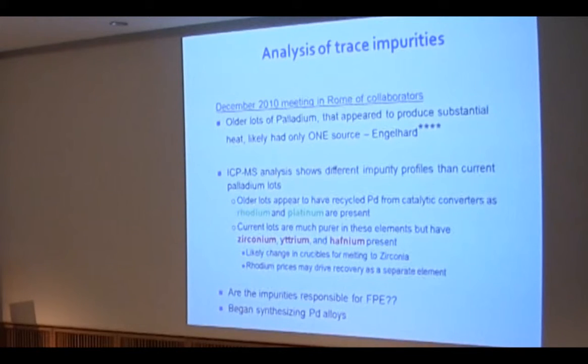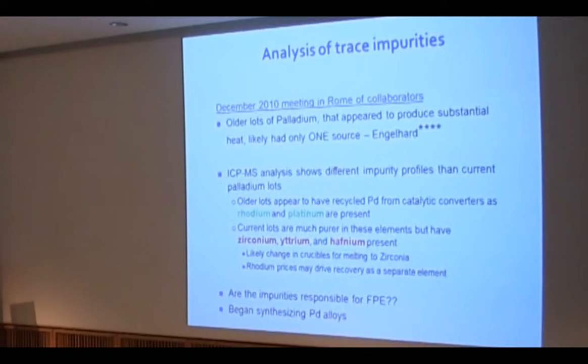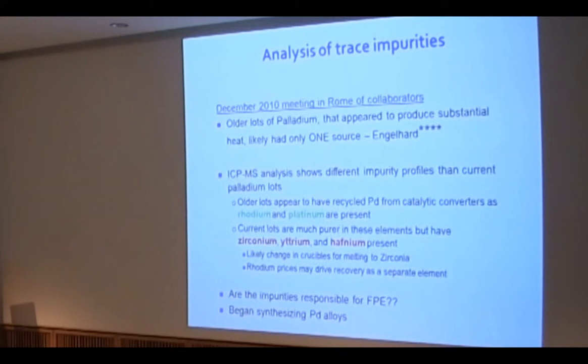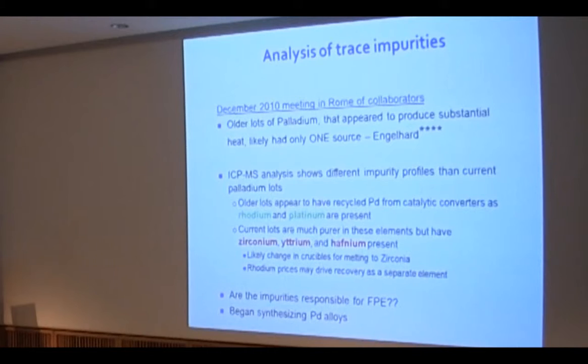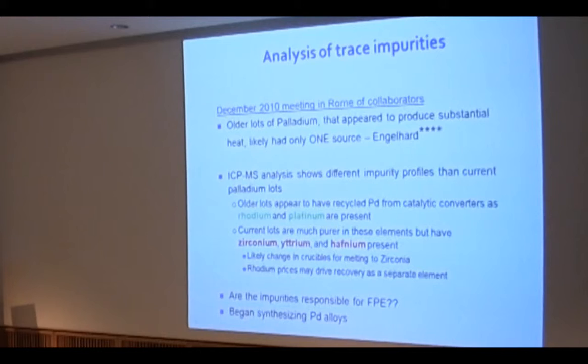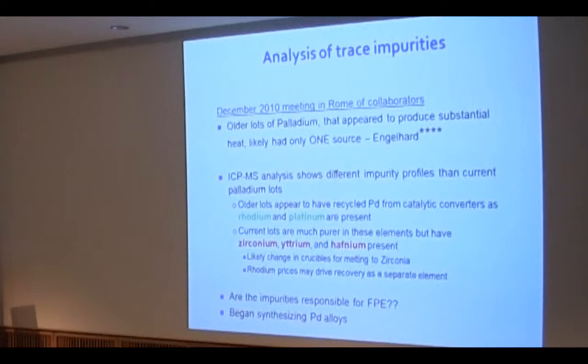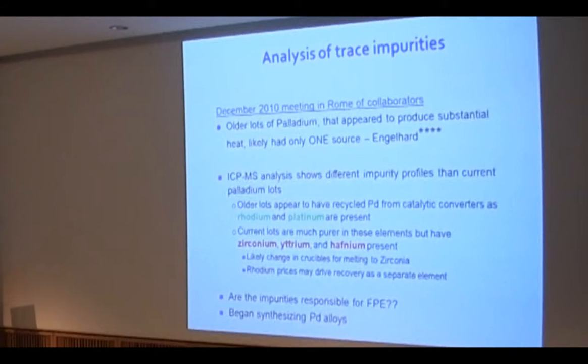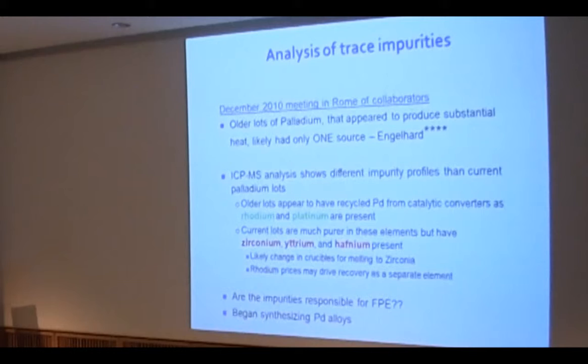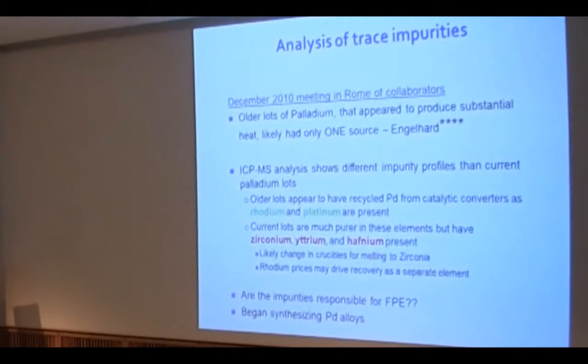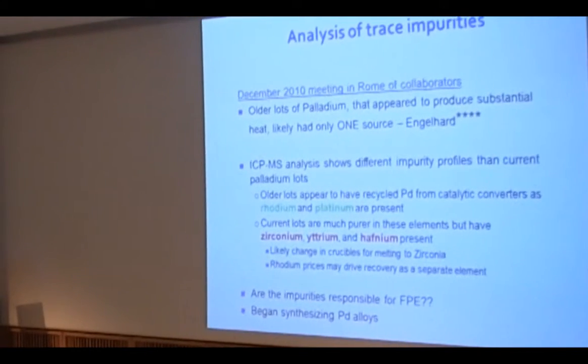So as a result of that, David went and Jinghao went, and they tried to do a tedious thing of varying the zirconium every 5 or 10% to finally get down, and never found that made any difference. So this is a caveat. I really believe in the talk that Vittorio gave, that he's onto something with that morphology. We at NRL have found and defined morphology similar to what he was describing, and we have sent our samples to him for these power spectral density measurements, that you do want that morphology.